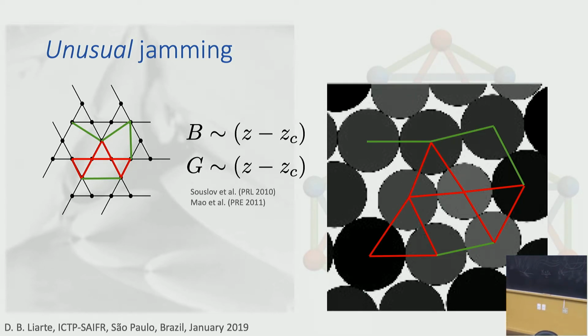Are they touching? Or, I mean, are they perfect circles, or are they not perfect circles? No, I mean, yeah, they are touching. This is done in the computer, for instance, and you have to have a threshold for when they are touching or not. So what's the threshold? That's what I'm asking. This is arbitrary. You can choose the threshold to be as small as the computer can manage. No, that's not true. If the threshold is very, very small, then you may lose some contact. No, the idea is that this is for spheres touching each other.